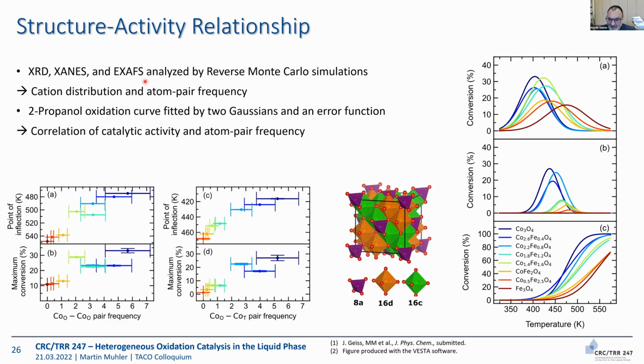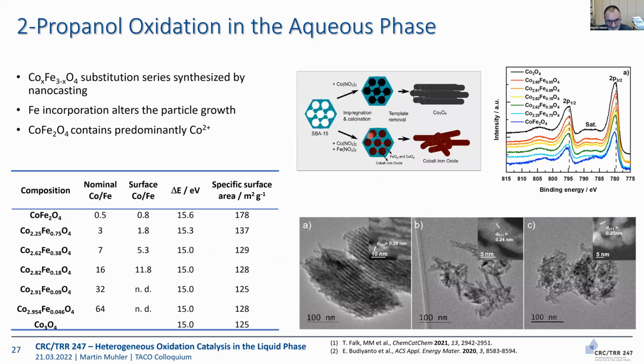simultaneously. And there it seems that we can establish a correlation between the low temperature, the middle temperature, and the high temperature channel, and we can correlate it with atom pair frequencies. Atom pair frequency means the likelihood that we have pairs of ions, cobalt on octahedral sites, octahedral and tetrahedral sites, and Co3O4 always wins, is the best catalyst. So these are quite nice results, I think.